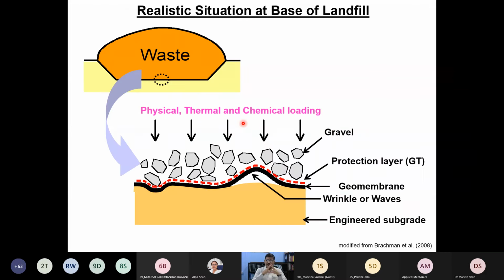But is the process the same in a landfill, or if the membrane is simply immersed into a leachate, where the leachate has a certain concentration, certain temperature, certain chemical activity, which we maintain? Earlier, most of the oxidation phenomena were studied on free membranes just dipped into the leachate. However, at a given landfill base, your geomembrane is not only subjected to the chemical leachate, not only subjected to the thermal effects. Because of the decomposition of the waste, the temperature of the basal liner may increase maybe even up to 85 degrees. This is quite possible. 55 is quite common.